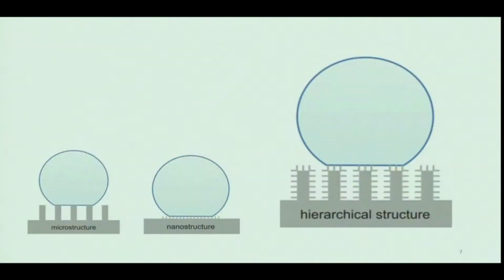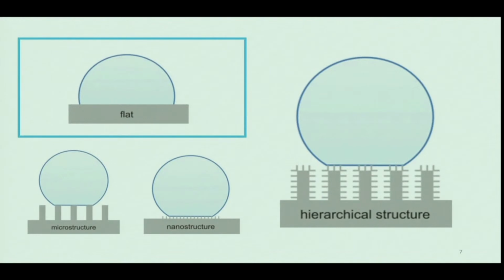But why do we need this combination? What about only microstructures? Or only nanostructures? Well, let's understand why the hierarchical structures is the desired output. Starting from a flat surface, which is the same as we have in plastic bottles that we buy nowadays. The water droplets is spread out on the surface. And also, the contact area between the water droplet and the surface is the largest, as you can see on the red line. And that's why the droplet gets stuck onto the material.